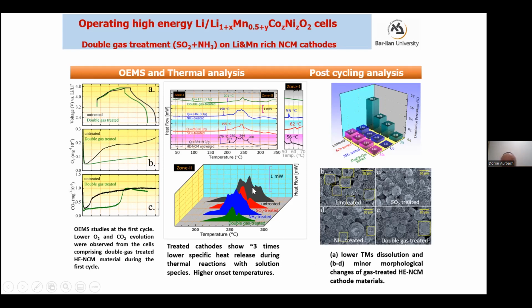Look at the black chart here and the green chart. You can see a very pronounced difference, which demonstrates very nicely the thermal stabilization. Now, when we look at another important parameter, we take the negative electrode and we look at how much transition metals we have on the negative electrode. Now we can measure the level of dissolution of transition metal from the cathodes to the electrolyte solution. This is a big problem because usually with all this cathode material, we have dissolution of the transition metal cations, and they go to the negative electrode. We have deposition of transition metal there. It's like needles, and they destroy the passivation of the negative electrode.